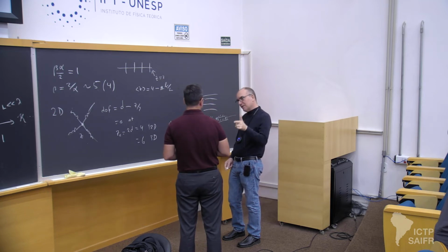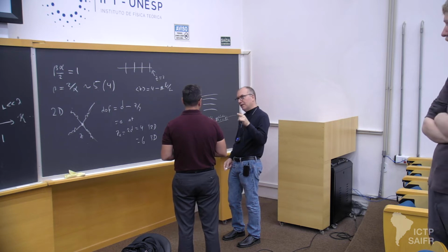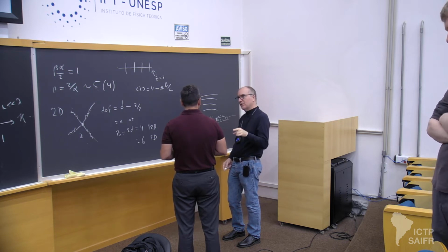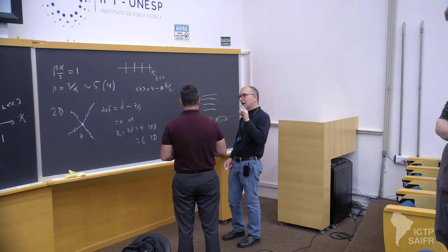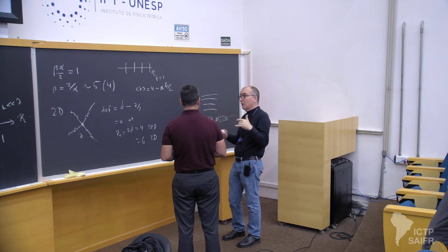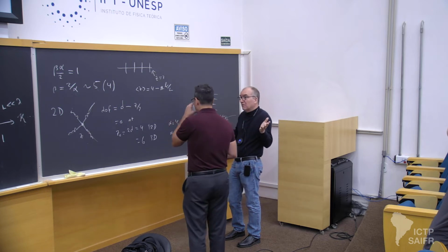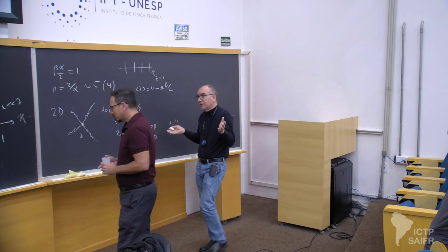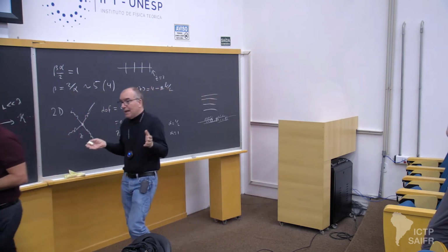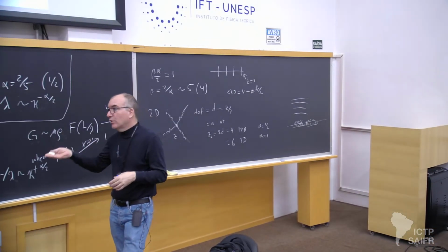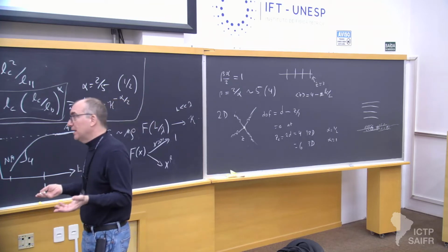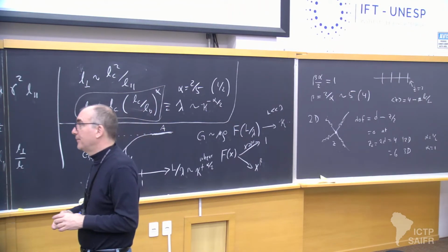Yeah, so I'm going to start talking tomorrow about the strain control transition. And it's important to note that that transition can occur with macroscopic strains as small as 5%, at which point you're not getting significant macroscopic alignment. Obviously, if it's occurring at 30, 40%, then you're already starting to get significant alignment.